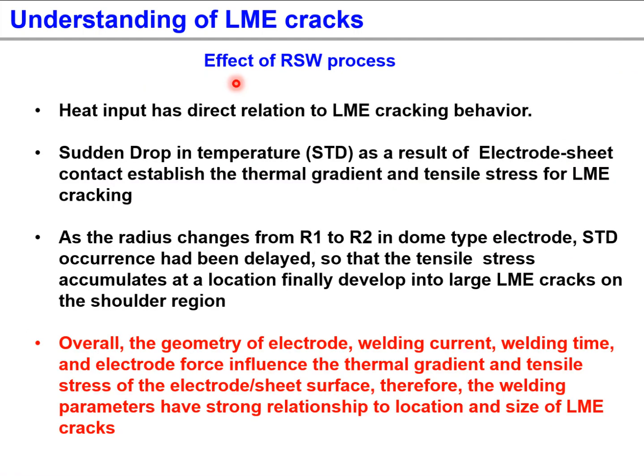To summarize the effect of resistance spot welding processes on LME cracks, heat input has a direct relation to LME cracking behavior. Sudden temperature drop as a result of the electrode to sheet contact establishes the thermal gradient and tensile stresses for liquid metal embrittlement cracking. As the radius changes from R1 to R2 in the dome-type electrode, the sudden temperature drop occurrence has been delayed, so that the tensile stresses accumulate at the location and finally develop into large LME cracks on the shoulder region.